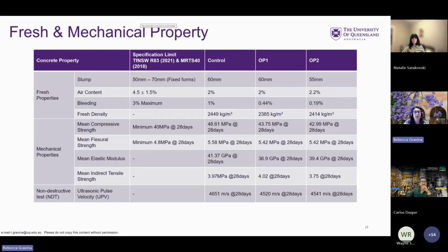In terms of the fresh and mechanical properties that we've been able to achieve, the important thing here is that the minimum compressive strength has been achieved with the two optimised mixes, OP1 and OP2. The air contents and the slumps were targeted and very similar to the control mix. The densities vary a little bit, but are still similar to the control. The modulus of elasticity was a little bit less, and that's probably related to the content of the recycled concrete aggregate in there also, and our indirect tensile strengths were quite similar.